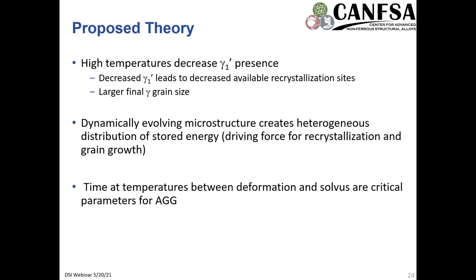One of the proposed theories about how the microstructure is evolving here is that this high temperature deformation is decreasing the primary gamma prime presence, and this is reducing the site availability for recrystallization, the number of sites, so that we have a larger final gamma grain size. This is in theory quite consistent with, as well as experimentally what we've been observing. And this dynamically evolving microstructure that occurs throughout deformation, as we saw with the three grain group distribution of stored energy and sizes, creates this really heterogeneous distribution of stored energy that results in the driving force for recrystallization and grain growth.